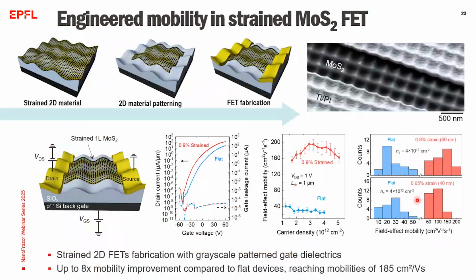After the material transfer on these grayscale surfaces and introduction of strain in 2D materials, again it's MoS2 in this case, the 2D material is patterned to form a semiconductor channel. And finally, source and drain electrodes are deposited through lift-off metallization. And for strained transistors, we observe up to eightfold mobility enhancement compared to flat, so unstrained, transistors, for around 1% tensile strain, reaching mobilities of around 185. And for approximately 0.6% strain, up to 5 times enhancement is achieved, which is directly correlated to the strain level induced within the material.